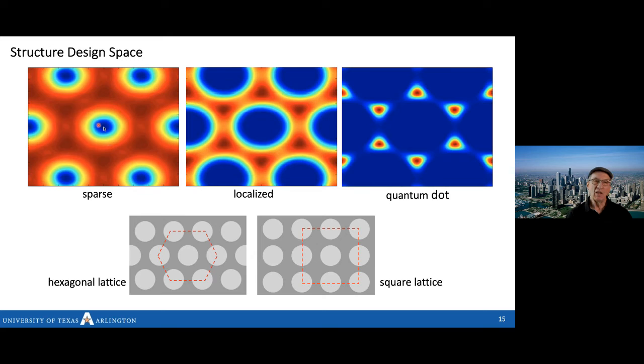Now let's look at those calculated, not cartoon version of the carrier density. So deepest red is where there's the most electrons, and blue means essentially no electrons. And these are the three cases again: the sparse, localized, and the quantum dot. You can see the carriers are isolated in the quantum dot, and these are isolated from each other, but not so isolated. And then this sample basically is only slightly perturbed.